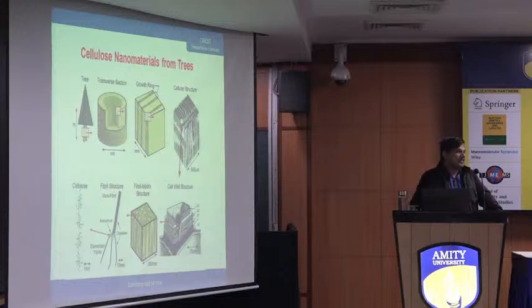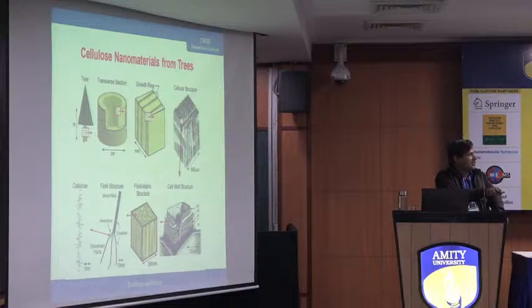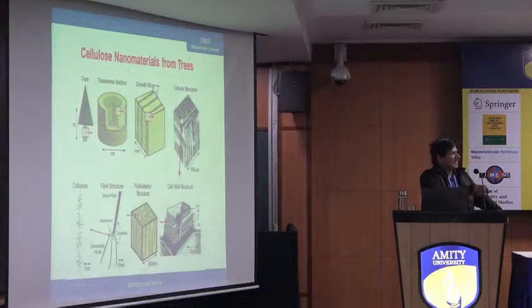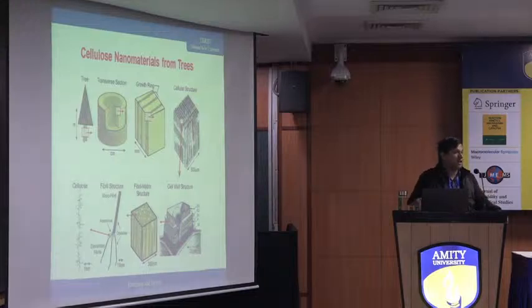So why are agricultural crops very important for this technique? This is how nature looks. You can take a tree, cut this portion, and you end up with the transverse section, which is on a centimeter scale. Cut this portion again, this centimeter becomes millimeter. Then cut this portion, you end up with a cellular structure, about 500 micrometer. Cut this one, you end up with a cell wall structure, about 25 micrometer. Cut this portion, you end up with the fibril matrix structure, about 300 nanometer. Cut this fibril matrix, you end up with the fibril structure. Then when you cut this one, you end up with the cellulose, which is about 1 nanometer.